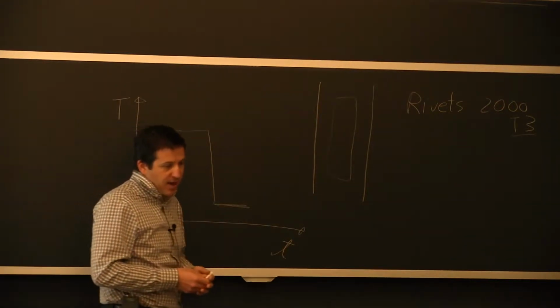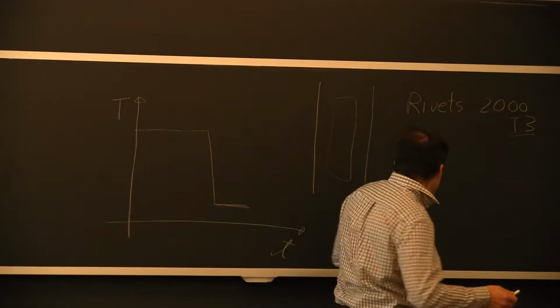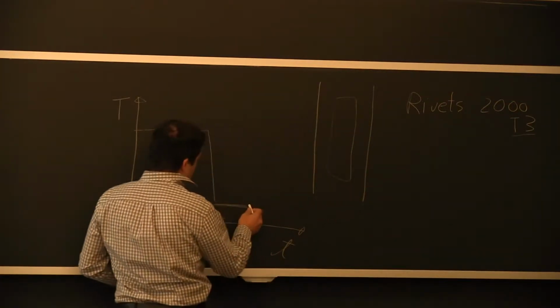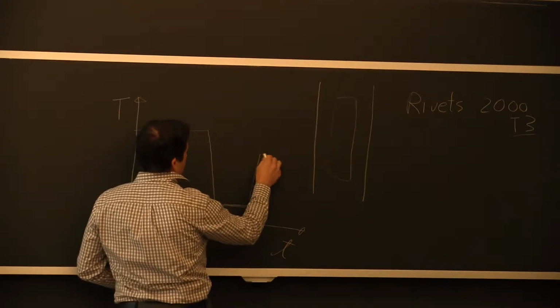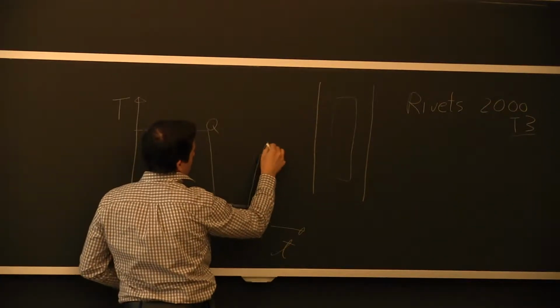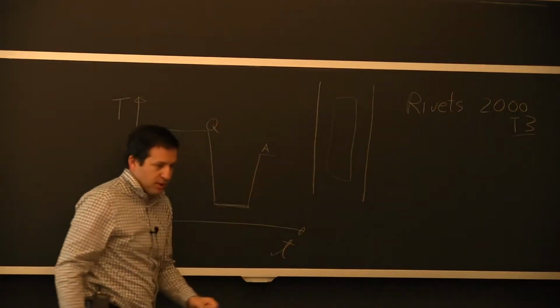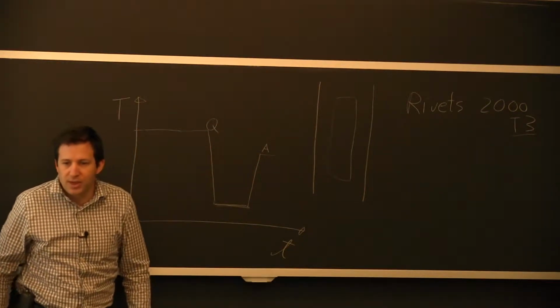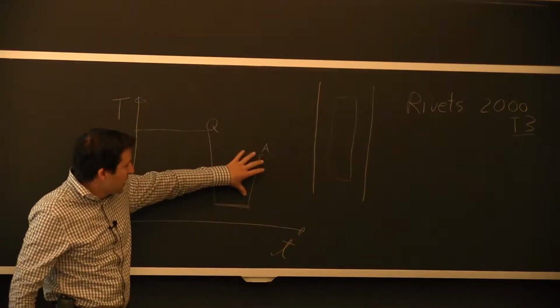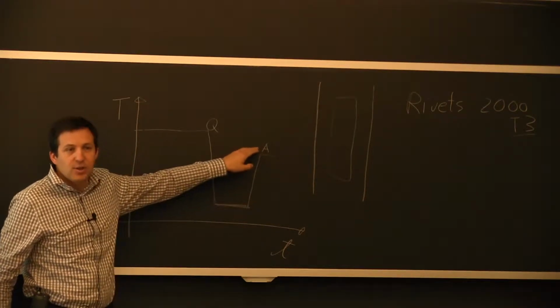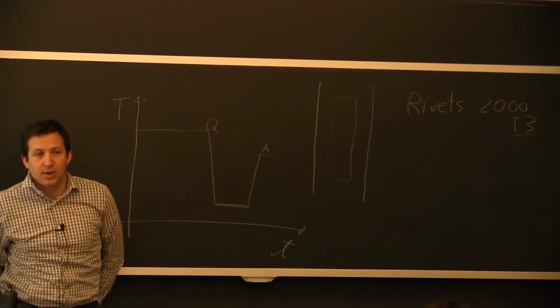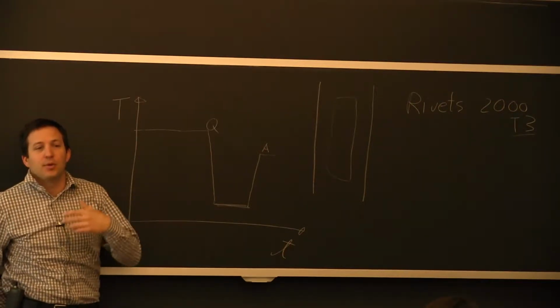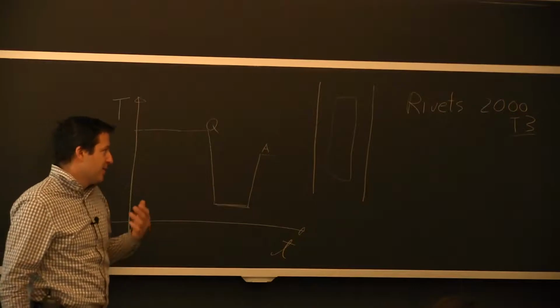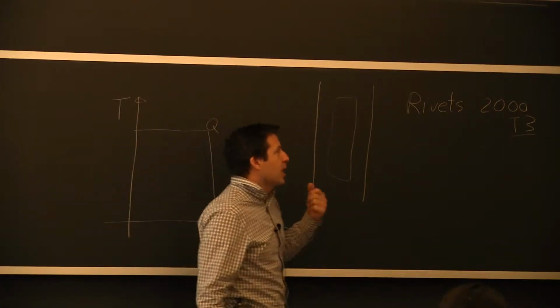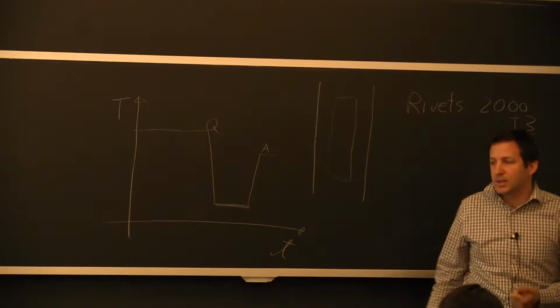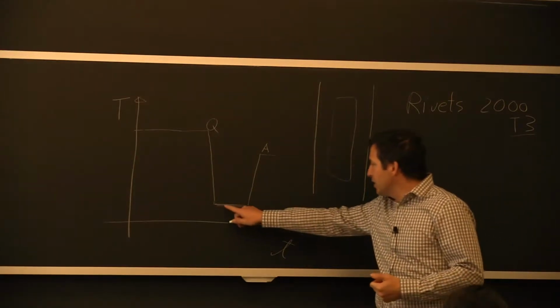A lot of alloys, the 6000 series, the 7000 series that Professor Eager mentioned yesterday, what you do is aging. So this was the quenching, and here we're going to age the microstructure. It's relatively low temperature, and that's why Professor Eager was saying sometime in service, that aging process could be a cause for deterioration of properties, and that's if you over-age. What would probably help you a little bit here is there's a lot going on after you quench.